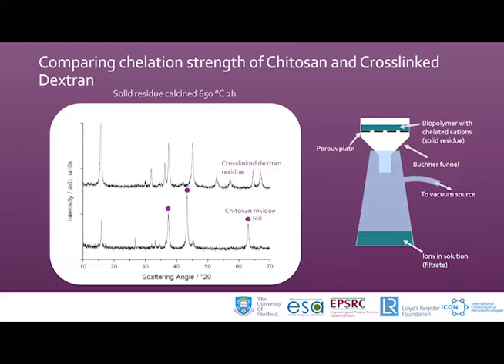So they are likely to persist at higher temperatures, as we have seen, making it harder to form a phase pure material. Ideally, we need to find a biotemplate that can bind all these cations similarly to some extent. This would ensure a more homogeneous mixture of these atoms at an atomic level, and it would prevent agglomeration and growth of intermediate phases, so it's more likely to have less nickel oxide at the end of synthesis. That's something I am still pursuing.